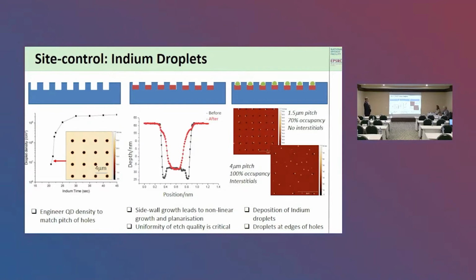There has been a significant challenge in the growth of the buffer by MOVPE, and these are quite shallow and narrow nanoholes. And what happens in MOVPE compared to MBE is that you get a lot of growth from the sidewall. So actually the control of this buffer layer has been very challenging. We often, when we first grew, got initially planarization. In other words, we removed the pattern. So we've had to develop this to make sure that we get good buffer layer formation within those holes.